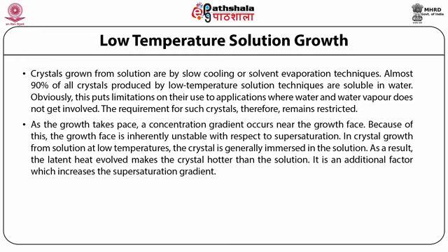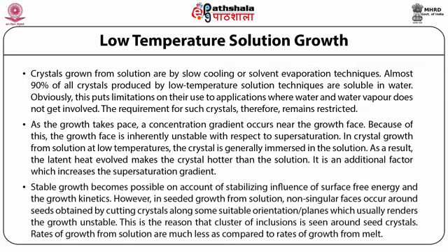In crystal growth from solution at low temperatures, the crystal is generally immersed in the solution. As a result, the latent heat evolved makes the crystal hotter than the solution. It is an additional factor which increases the supersaturation gradient. Stable growth becomes possible on account of the stabilizing influence of surface free energy and the growth kinetics. It is for this reason that stable growth phases are always singular in solution growth.